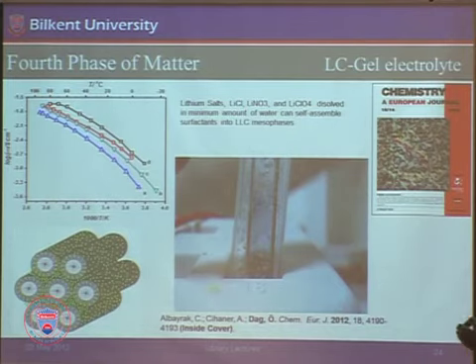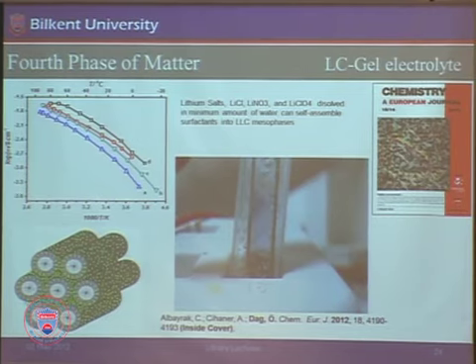And when we discovered that, we said that this field is not limited to those transition metals with these water spheres. We can add that extra water into these types of salts. Lithium is very important in ionic conductivities for ionic membranes, basically. In this cover, we discovered that lithium salts also form liquid crystals. You can form gels. And this is a small application, basically. Maybe I can stop after this.